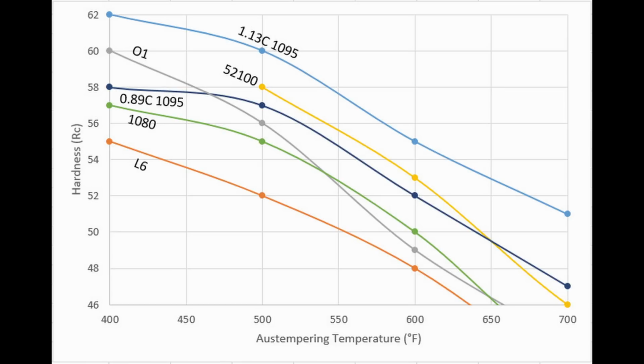If we're holding the steel at a 600 or 700 degree austempering temperature, the hardness will be quite low, below 55 Rockwell, even for a pretty high carbon steel. And as we move lower, down to 500 degrees, 400 degrees Fahrenheit, then we're approaching the 58 to 62 Rockwell range, depending on the carbon content of the steel.